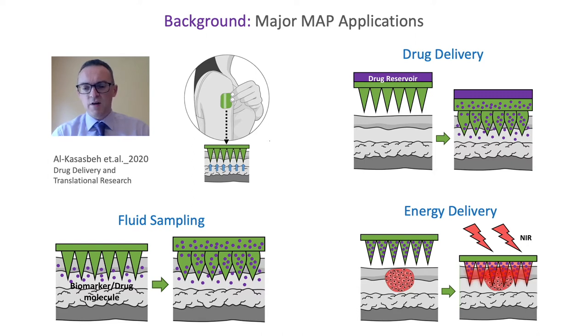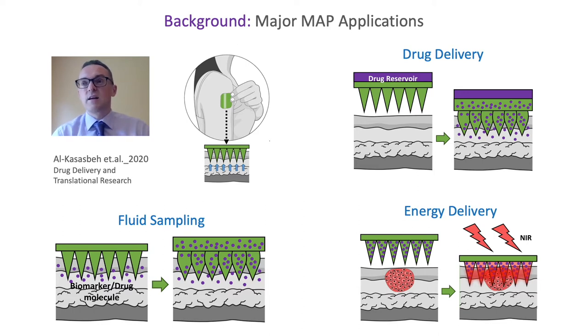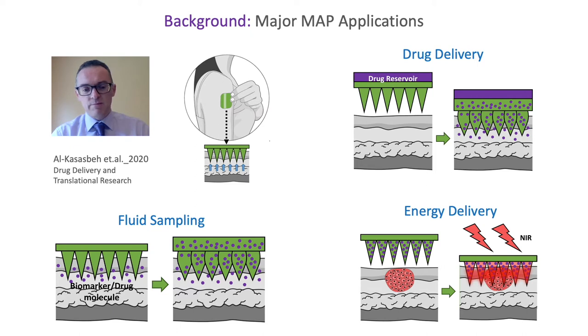The microneedles are optically transparent to near-infrared light but allow heat to diffuse into the surrounding skin. Applying these microneedles to a skin lesion and then applying near-infrared light for even a matter of seconds will cause the microneedles, through the action of the plasmonic gold nanorods, to heat up and destroy the neoplastic lesion, allowing the skin to heal without scarring — a potential benefit over surgical excision. A final important application is fluid sampling.